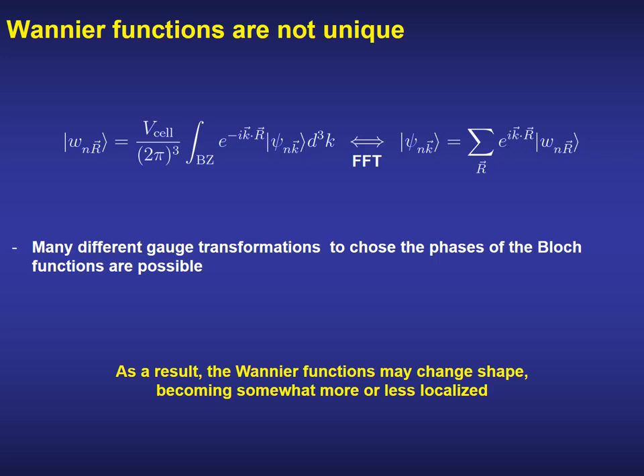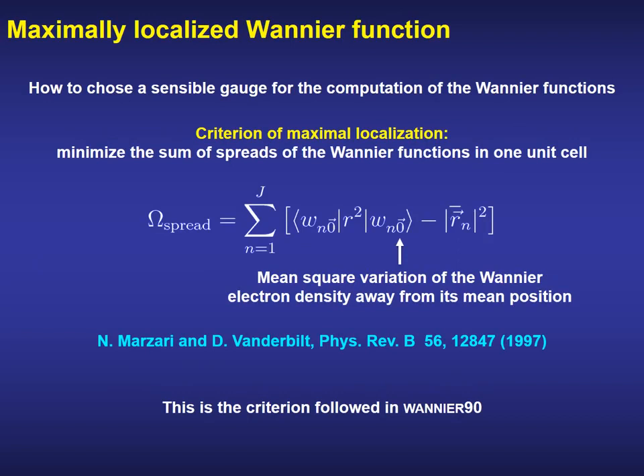One important issue is that the Wannier functions are not univocally defined. As it has been emphasized since the very beginning of the lecture, the Wannier functions are constructed from a unitary transformation of the Bloch functions. Since the phase of these Bloch functions are not univocally defined, many different choices or gauges are possible. A change of the gauge would result in Wannier functions that change the shape, becoming somewhat more or less localized in space. A way of choosing a sensible gauge was proposed by Marzari and Vanderbilt in this celebrated paper. The guiding rule is the minimization of the spreading defined in this equation from the diagonal elements of the square of the position operator and the square of the center of the Wanniers. This maximal localization criterion is the one followed in Wannier90.